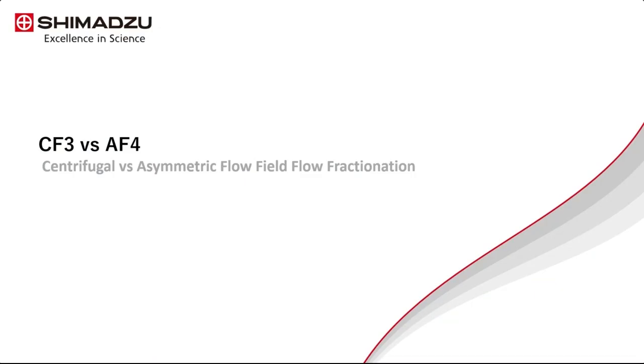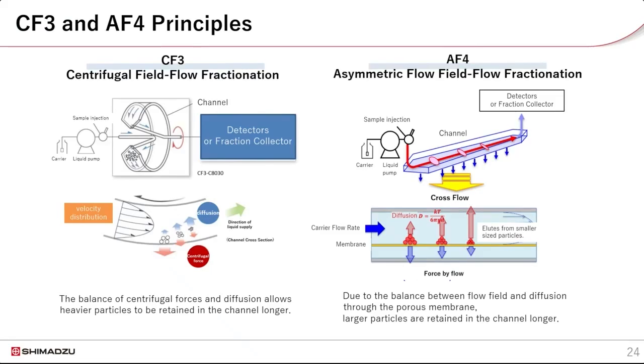And now, let us compare CF3 with the AF4 or the asymmetric flow field flow fractionation technique. So AF4 works using a membrane. The carrier flow is parallel to the membrane and a small pressure is generated inside the separation chamber. By controlling this pressure, the carrier flow rate, and the porosity of the membrane, a membrane filtration of the particles is achieved, with the smaller particles eluting first, followed by the larger particles. CF3, on the other hand, works completely differently using a centrifugal field, as mentioned.